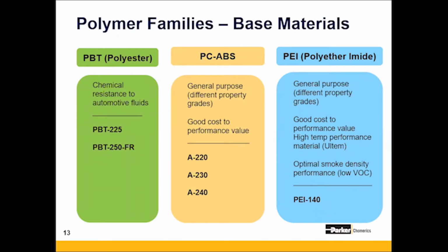And the two different types of PBT materials are a PBT 225 and a PBT 250 FR, that FR being a flame retardant variant. In the middle, you have a PC ABS, which is a polycarbonate ABS alloy. And that actually has a few different grades, and it's a great cost to performance value. So A220, 230, and 240 represent the different loading levels of conductive fillers within the polymers, with a high temperature and flame resistant variants available in all of those. And finally, you have a PEI on the right side, which is a polyether imide, or an Ultem-based polymer, which is primarily used for high performance military applications or applications where you see high temperature requirements or where optimal smoke density performance is needed.